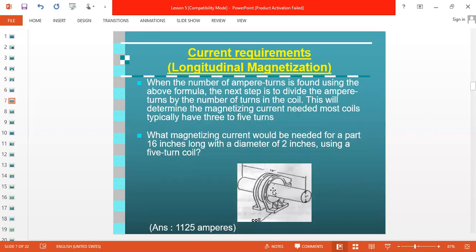Now in the coil shot, look here very carefully. This 18 inch we can cover from both sides of the coil, meaning 9 inch on the left side and 9 inch on the right side from the center of the coil. Suppose our job is 36 inch long. Then we have to give 2 shots. After this magnetization, we shift the job and cover the new, remaining area of 16 or 18 inch.